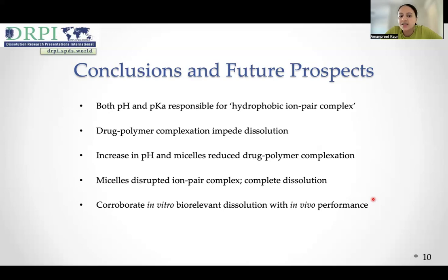Micelles, on the other hand, disrupted ion pair complexation by solubilizing bedaquiline, which freed carboxylic acid groups for hydration and solubilization, which is why we observed improved release profiles in fasted state version 1 and fed state version 2 media. However, it is important to establish relationship of in vitro biorelevant dissolution testing with in vivo performance of such complicated systems.